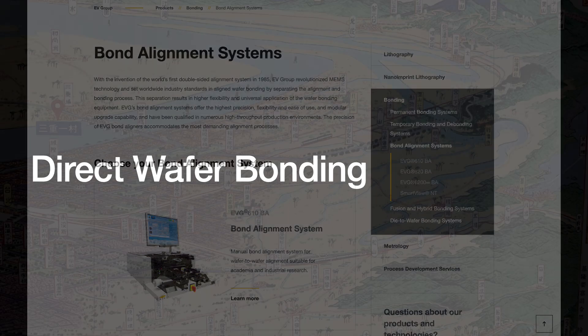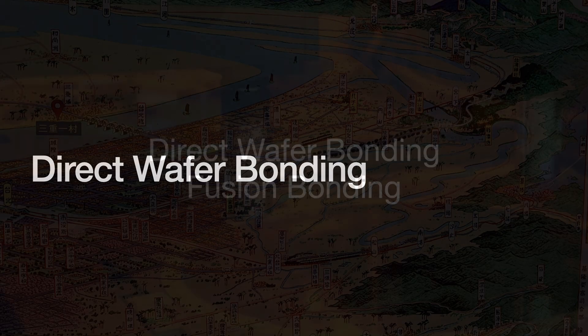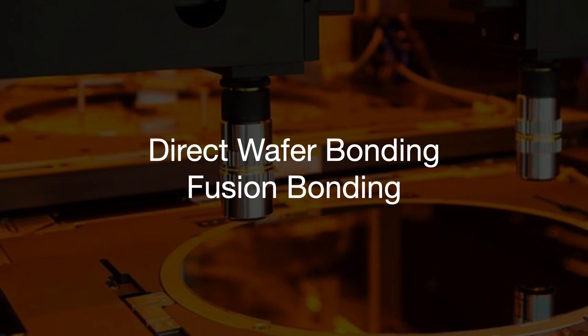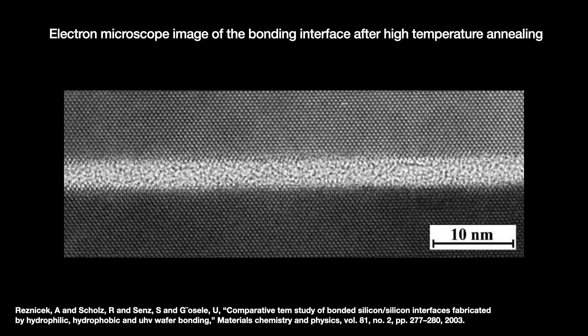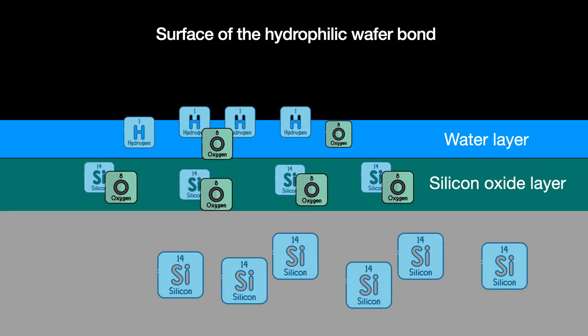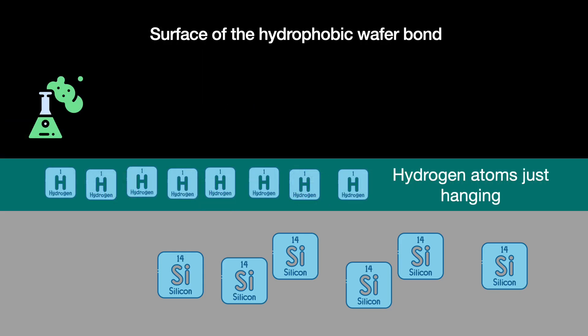Let us talk about the basic types of wafer bonding. Starting with the most ordinary, that is what we call direct wafer bonding. Sometimes also known as fusion bonding and the terms more or less mean the same thing. Direct wafer bonding is vanilla. We talked about the process earlier. Press together two wafers without an intermediate layer of material and then run them through an annealing step to solidify the bonds between wafers. Direct bonding has three subcategories based on the nature of the wafers' surfaces. First, we have a hydrophilic surface which has an oxide layer and water layer prior to bonding. Second, there is a hydrophobic surface where we removed said oxide layer with a casual dip in hydrofluoric acid. It's just hydrogen and silicon out there. And then finally, a third category of superclean silicon surfaces bonding under ultra-high vacuum or UHV conditions. This is out of our scope today, but I added it for completeness.